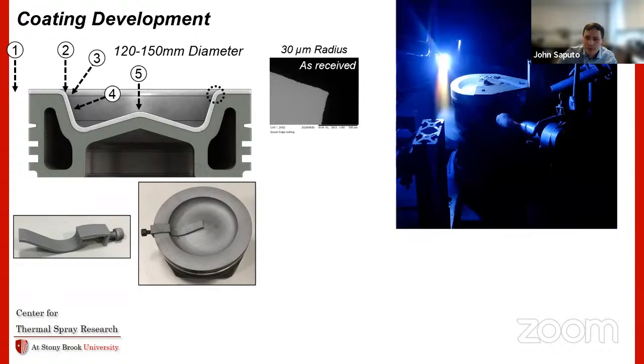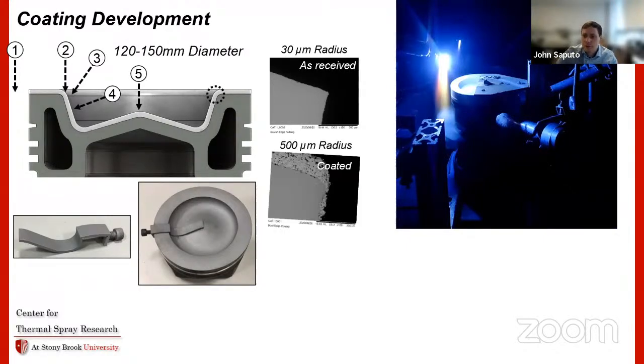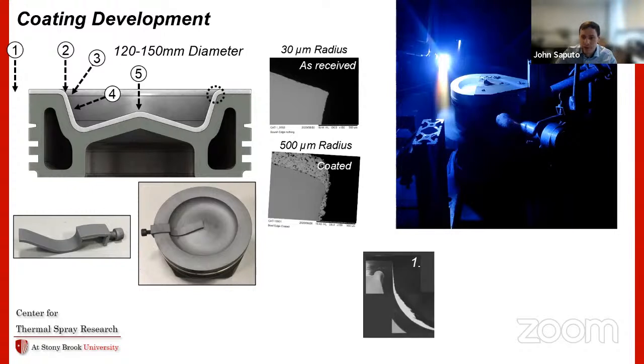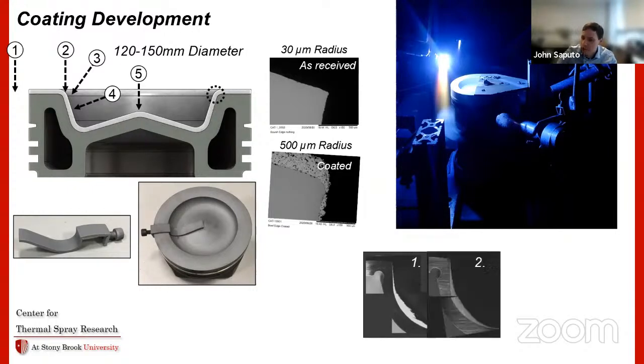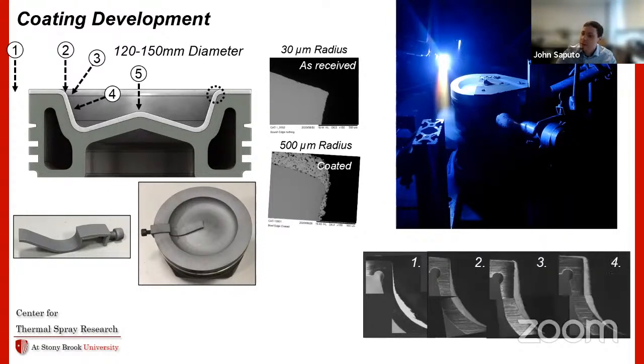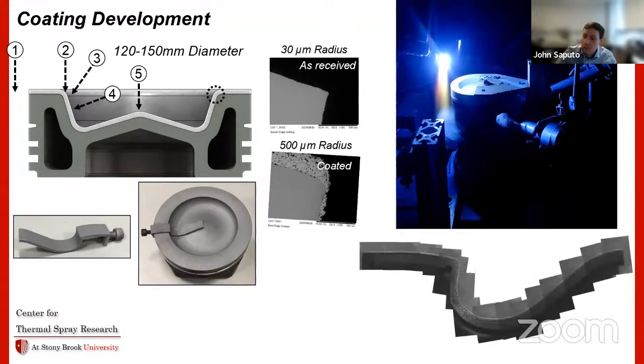So as you receive this, it looks something like this. And the first iteration of developing the coating tool path on top of this looks something like that. You turn that 30 microns into 500, and it's actually kind of terrible for these systems. So using those strips that I show on the left, you can iteratively go through this procedure of a brute force optimization, making the coating more and more uniform as you go until you get a uniform coating across the entire profile.